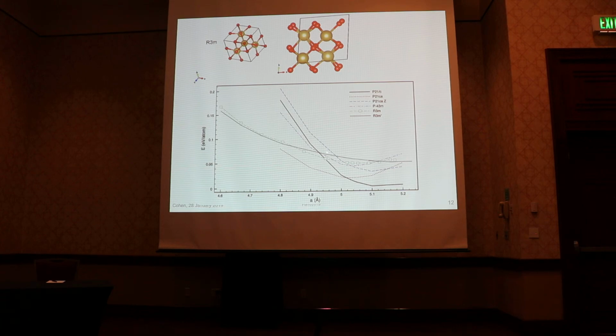Anyway, this also shows this rhombohedral phase, and this is one of the things that's very hard for me to get my mind around: I actually get slightly different results depending on what structure I start with. It turns out that there seem to be a lot of local minima. It's not just a random difference. I started with a different sign of the oxygen displacements relative to the zirconium displacements. In one case, I got this green curve for the rhombohedral structure versus strain, the other one, the black one. They're very similar, but they differ by 10 millielectronvolts per atom. So it is significantly different. You could consider this some measure of error, but I think it is also something real, that there are different local minima in this structure.